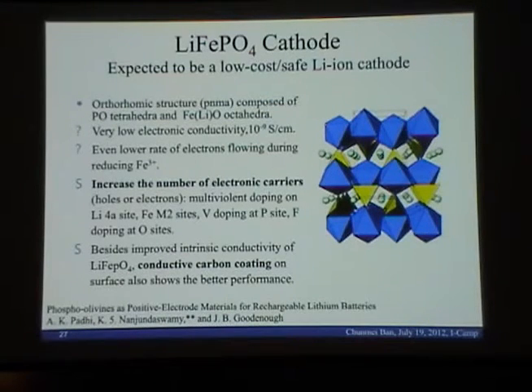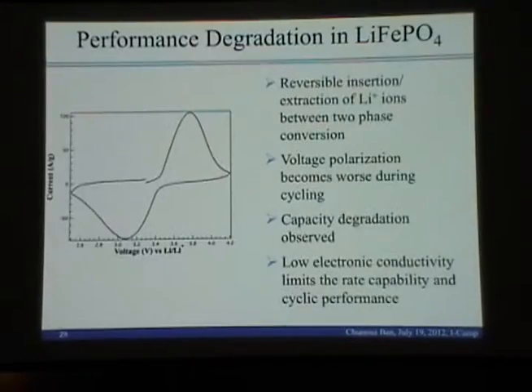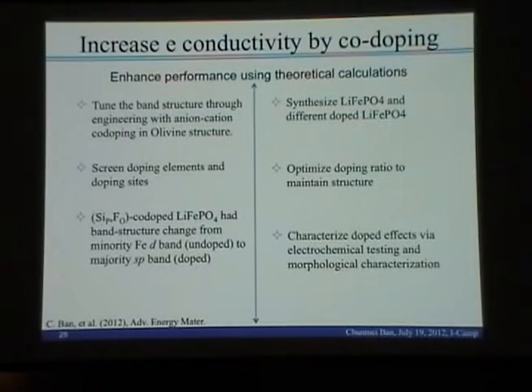So this is lithium iron phosphate. It's a very famous material because it has a low cost. But the thing is, lithium iron phosphate has really low conductivity. That means in the original paper, the researcher thought this one was only for low power applications. But after 10 years, MIT researchers found they can actually use a really high rate, like 1,000 C, to charge this material.